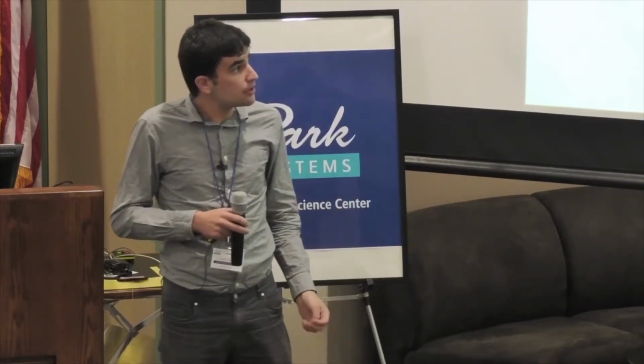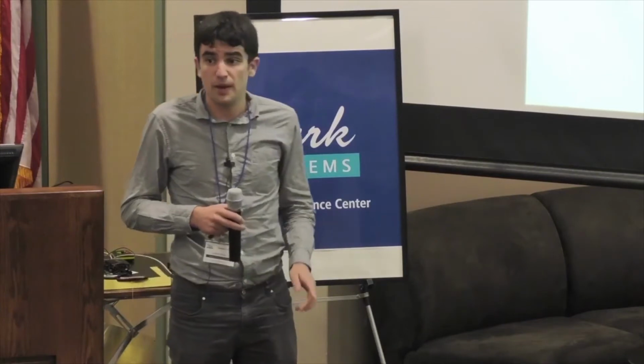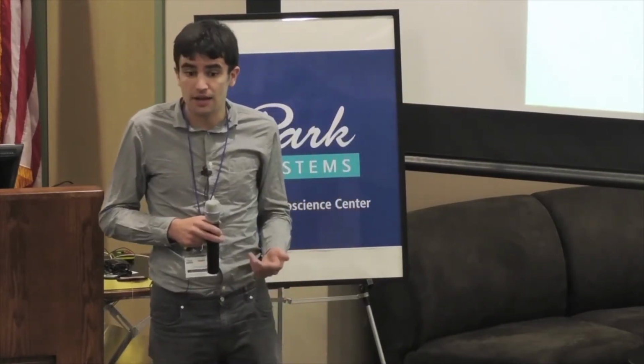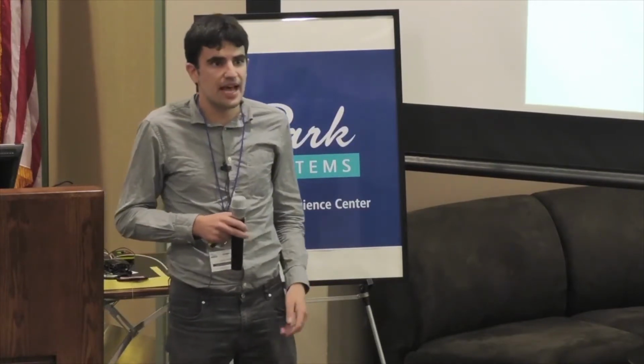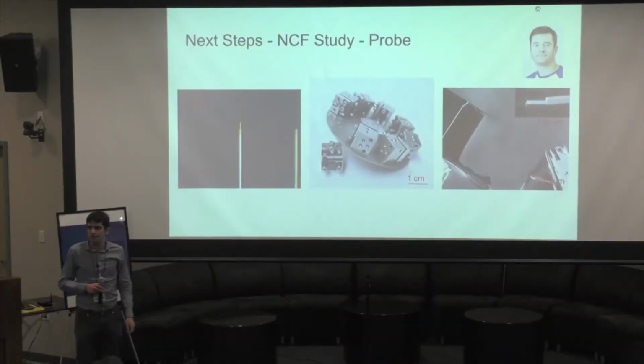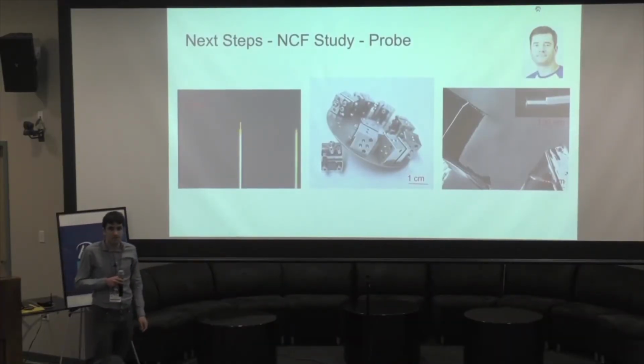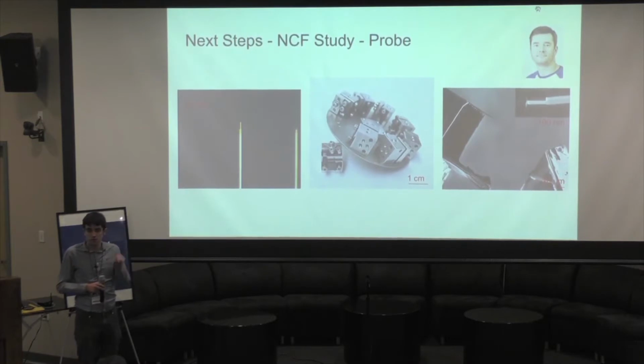So we've prepared cantilevers with, as well as their native silicon tips, gold and iron cobalt nanowires attached with a micromanipulator under an optical microscope. And then, with the collaboration of Ivan Shorubalko at EMPA in Switzerland, used a focused ion beam to mill the tips into a few different sizes and well-controlled shapes, so that we can control for tip area in non-contact friction measurements.